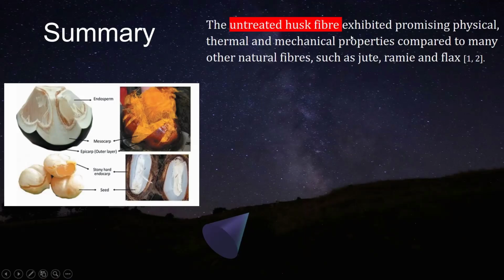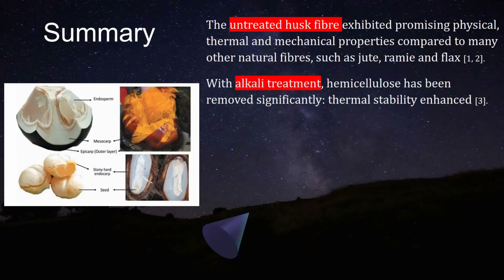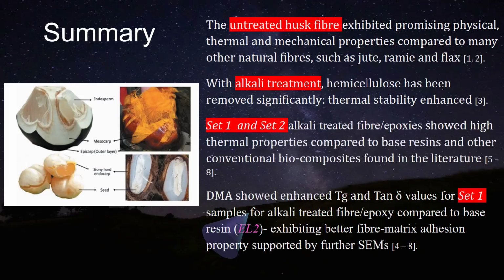The untreated fiber initially exhibited very promising physical, thermal, and mechanical properties compared to many other natural fibers found in the literature, such as jute, ramie, and flax. And then with alkali treatment, precisely, hemicellulose has been removed significantly, and therefore thermal stability enhanced, and we saw the result. We made two different sets of composites, set 1 and set 2. Alkali treated fiber showed high thermal properties from the TGA compared to the base resins and other conventional biocomposites found in the literature. And with the DMA, there is a diverse result we got.